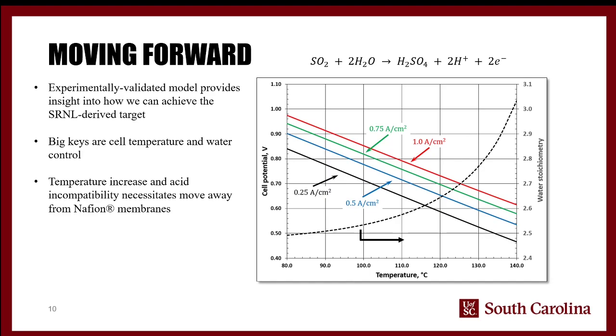You can change out the materials, you can change out the catalyst, you can start playing around with the temperature, with the current density, with the amount of water that you're putting into the system, things like that. And so the problem is those don't act independently. If you change one, you're probably changing at least 2 or 3 other ones, and that's going to have an effect on the current density you can achieve, the potential that you need to apply, and of course, something I mentioned at the beginning, the acid concentration that you produce.